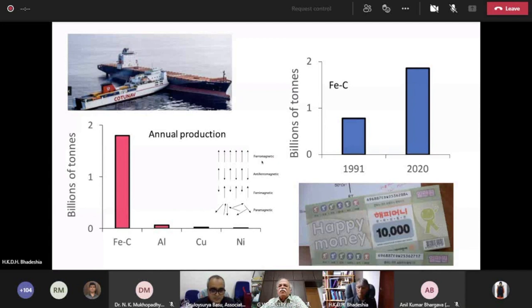And the third most important thing is that we can make very large structures in a very safe way. So here you have two ships colliding at 90 degrees, and yet neither of them have sunk. And that is because of the design of shipping steels, which are incredibly tough, can be welded, and so on. So we can make very large structures using steels. You cannot do that with any other engineering material. And these are the primary reasons why steel is so successful.